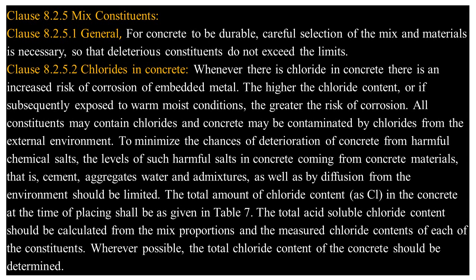be limited. The total amount of chloride content in the concrete at the time of placing shall be as given in Table 7. The total acid-soluble chloride content should be calculated from the mix proportions and the measured chloride contents of each of the constituents. Wherever possible, the total chloride content of the concrete should be determined.